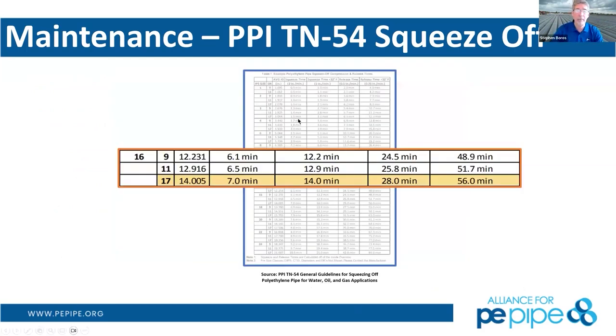So for example, within this document, TN54, it's going to tell you for every size pipe what the proper parameters are. So let's look at 16-inch DR9, pretty heavy wall pipe. That's going to have an ID of 12.2 inches. Your squeeze rate, bringing those two bars together, is going to be 2 inches per minute, the recommended value. And it's going to take you 6.1 minutes to squeeze that pipe totally closed with a proper amount of wall compression. If you're below 32 degrees, that time's going to double. Now your squeeze-off rate is only 1 inch per minute.